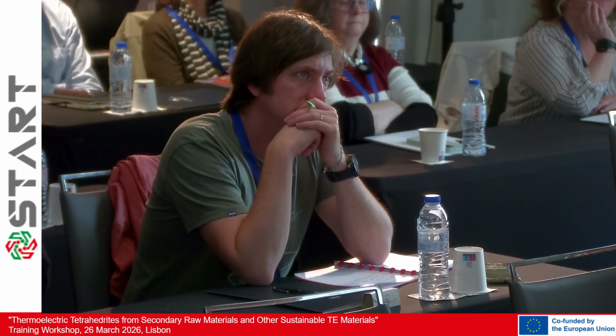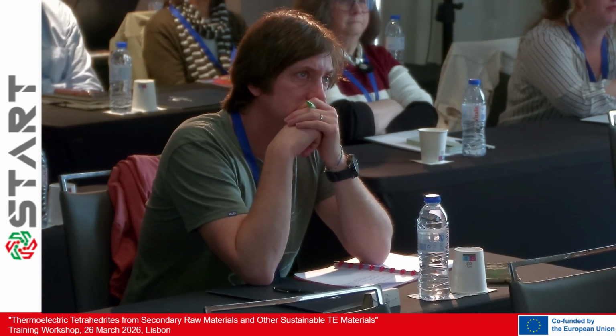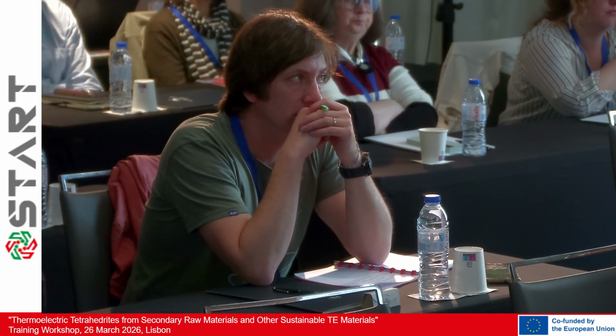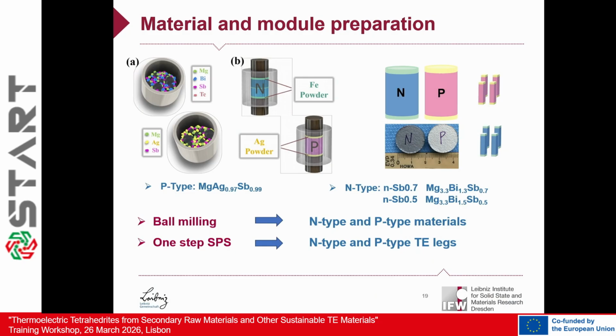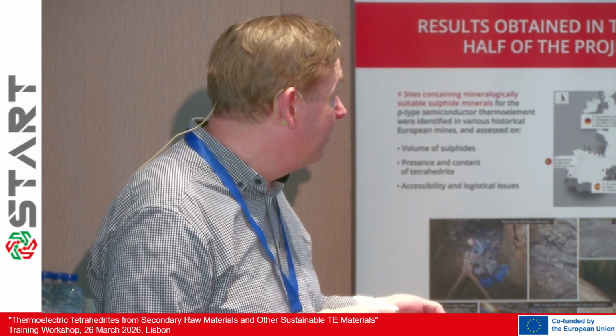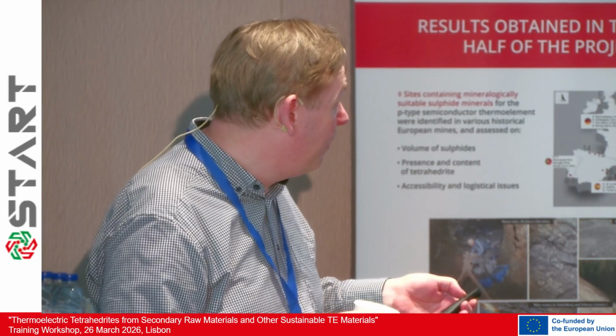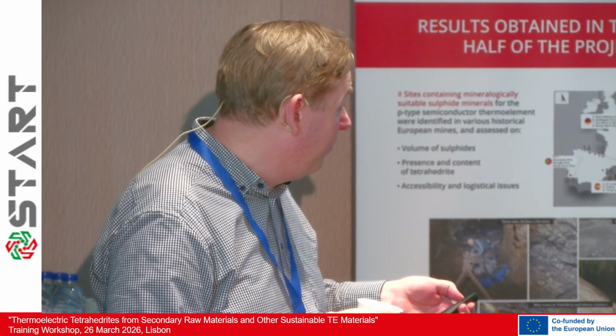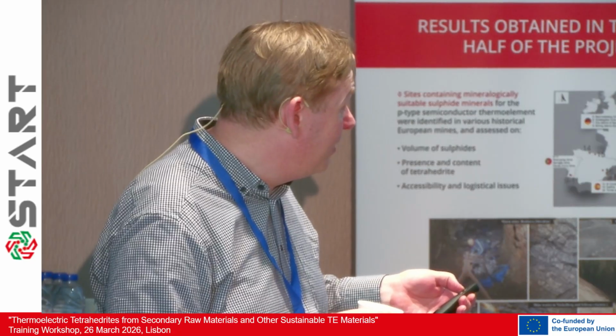Another challenge at the beginning was that the fabrication process was rather lengthy. You can see here fabricating the material, hot pressing, and then annealing for 7 days. In terms of industrial production, this is not very attractive. You will probably have to pay quite a high electricity bill. Therefore, we decided to do it in a much faster way. We directly do bulk mechanical alloying, taking directly the elements.